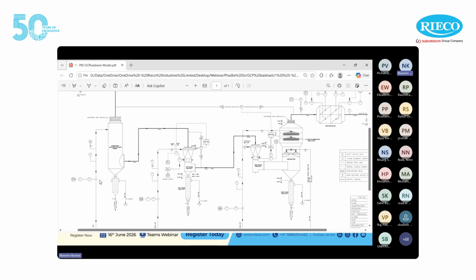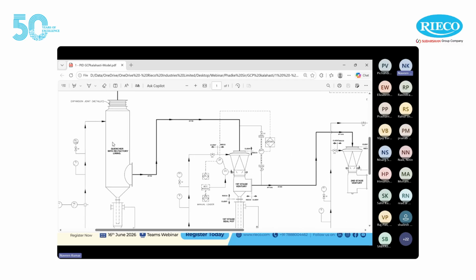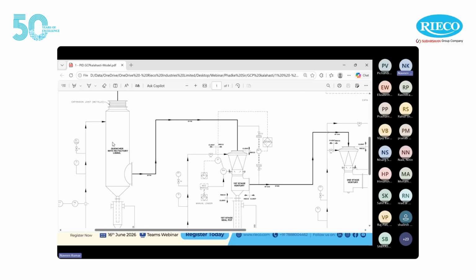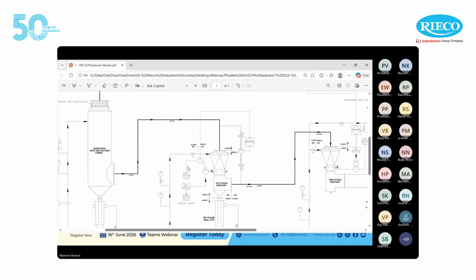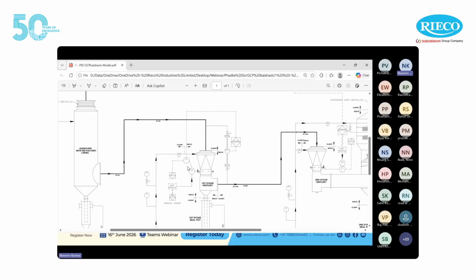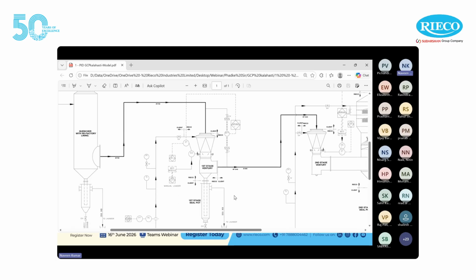What we can see on the screen is a typical gas cleaning plant where the hot gas from the mini blast furnace is first quenched in a saturator to bring down the temperature and then taken to the venturi. In the venturi, we have a system whereby we can reduce the cross section by throttling. This can be changed. There is flexibility in the design which allows you to change the cross section, whereby the turbulence in the throat of the venturi can be increased, and this is very important to ensure the high efficiencies required to deal with extremely fine powders.